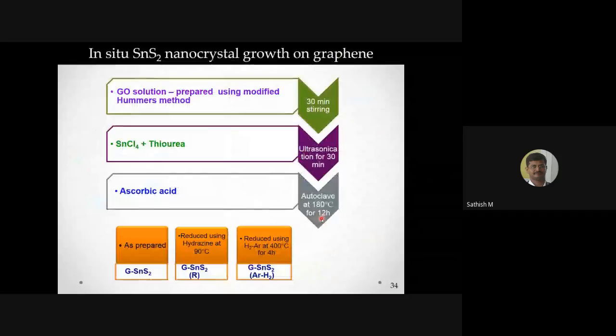Okay. So with this idea, we have made a graphene oxide solution prepared by the modified Hummers' method. We add some tin chloride and thiourea. You want to have a reducing atmosphere, otherwise the tin sulfide will become tin oxide. It will not be a tin sulfide. So you need some kind of reducing atmosphere, like ascorbic acid can do that job.